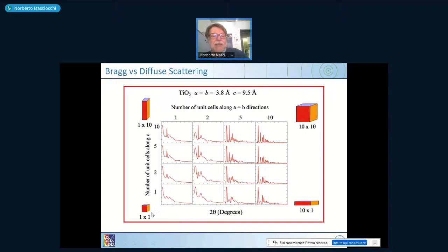Now let's make an increase of size which is only along one direction. You take one little cube and you stack many cubes on top. For example, what you see here, this tetragonal prism, is nothing else than a rod crystal made by 10 cubes on top of each other. You see that the trace you have here at the bottom is slightly different from the one on the top, in that one peak here is very sharp. This peak becomes sharper as you increase the size along C. That means that this peak is strictly related to this growth direction.